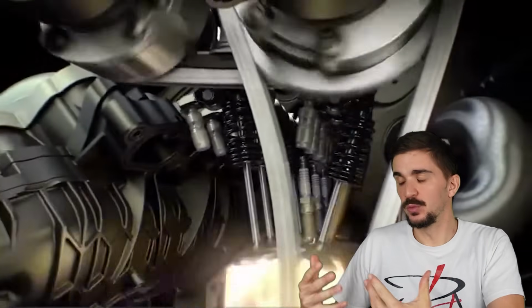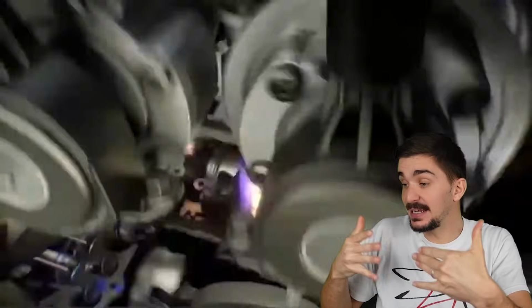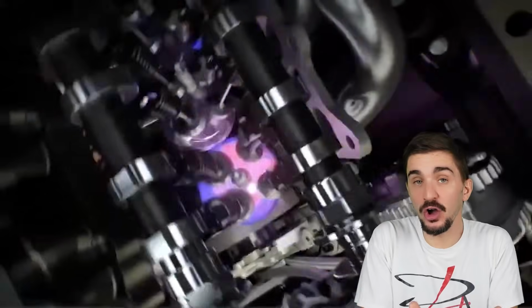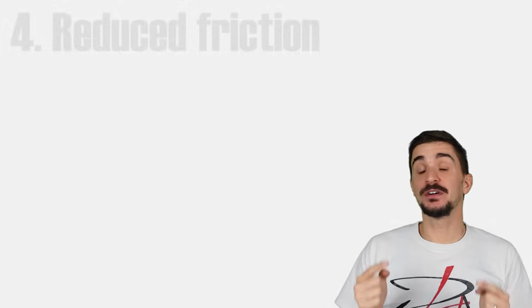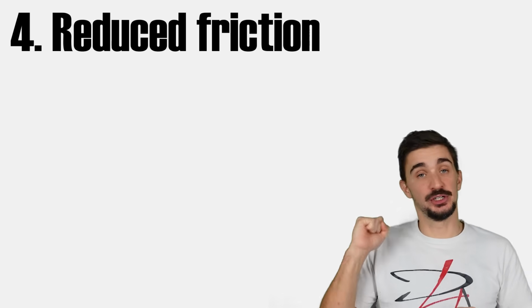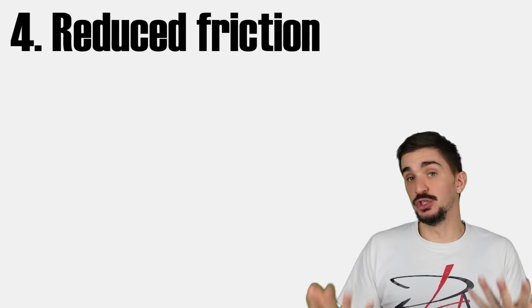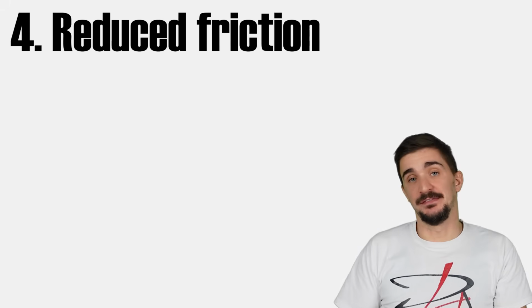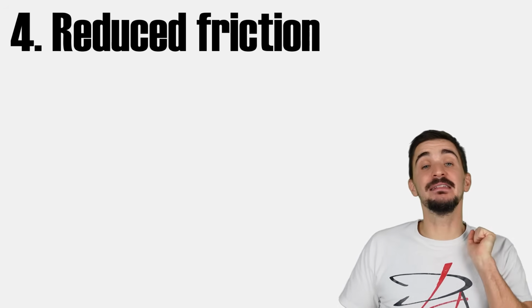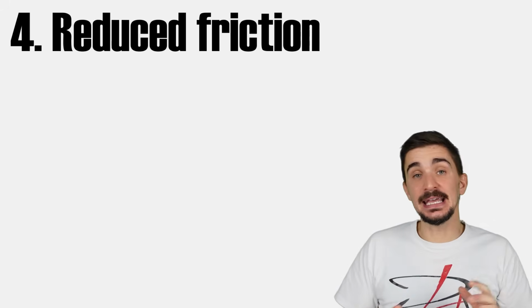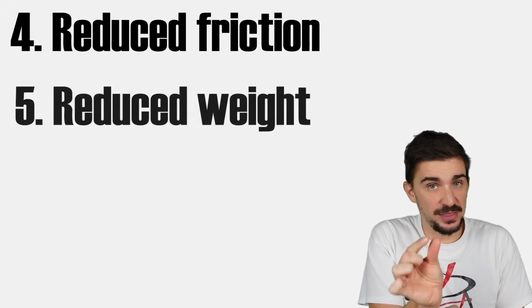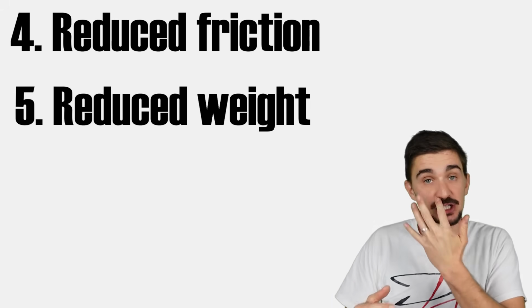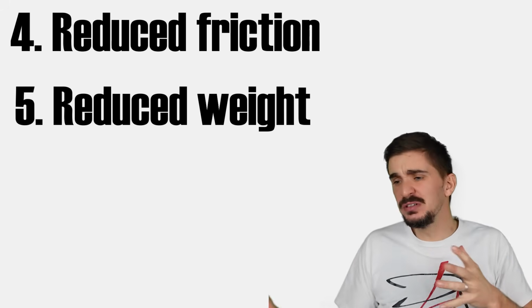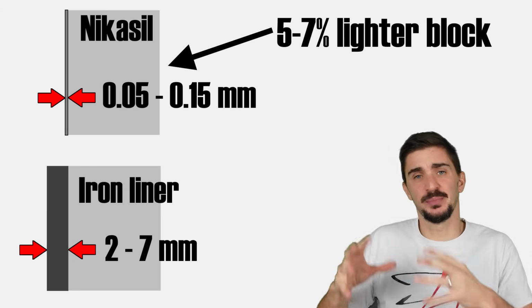The increased durability and wear resistance also of course means that the engine itself lasts longer with a Nikasil coating. Number 4, a Nikasil coating offers reduced friction compared to an iron sleeve, and reduced friction of course improves efficiency and performance. And finally, number 5, a Nikasil coating is much thinner, there's much less material, so we're actually saving weight, usually about 5 to 7% per engine block.